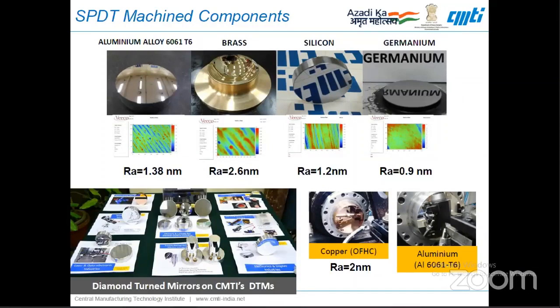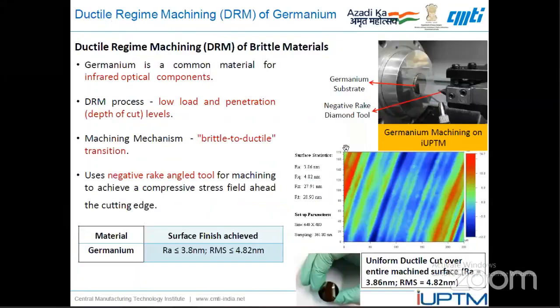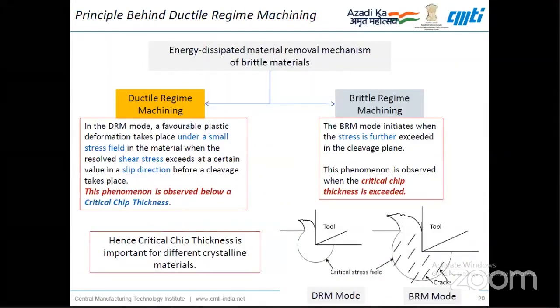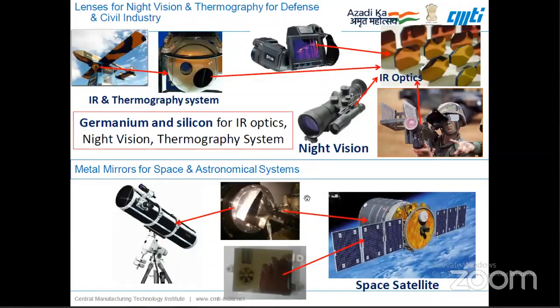But here we use a process called ductile regime machining, where we use a negative rake angle tool, which gives a very high compressive force on the surface of the machined component, like germanium, so that the surface doesn't crack. This way we are able to machine a mirror finish on components like germanium and silicon. Other parameters like critical depth of cut and process feed parameters also play a major role. The critical thickness for different materials is very important to get a very good surface finish on these brittle materials. We'll now look at the applications where diamond turning is widely used.